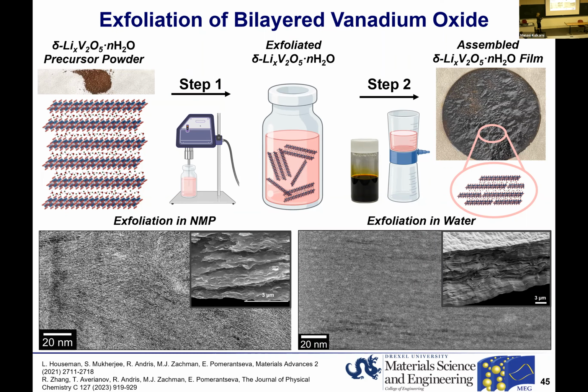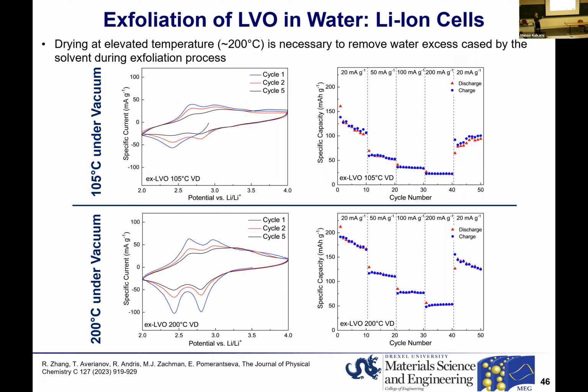When we used NMP as a solvent, the film had a lot of porosity. All the layers have some curvature and some pores forming between the nanoflakes. But when we used water, you see these layers are much more straight, and the nanoflakes cannot be distinguished in this case. So it's a very different structure. By using different solvents in the sonication process, we can control the structure of the final film. So we did look at the electrochemical behavior of the film obtained in water.